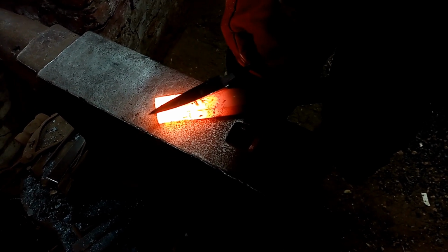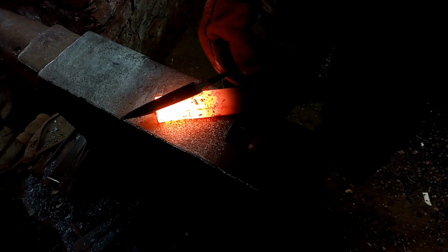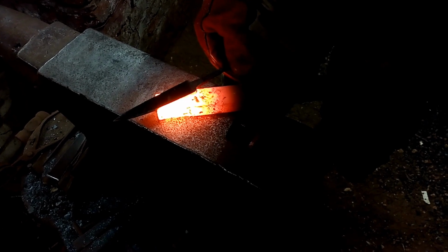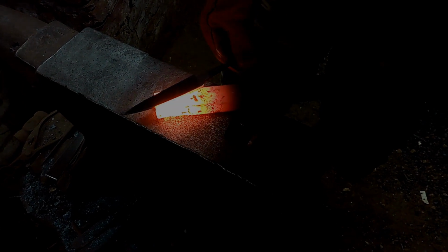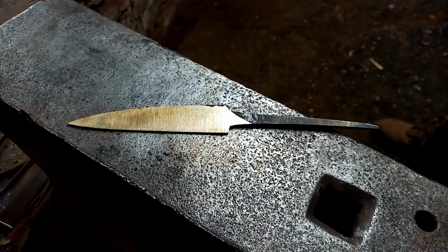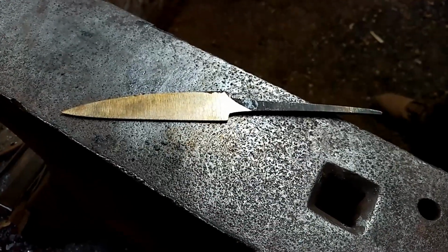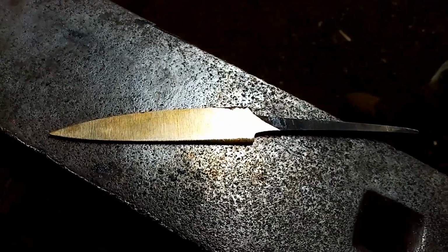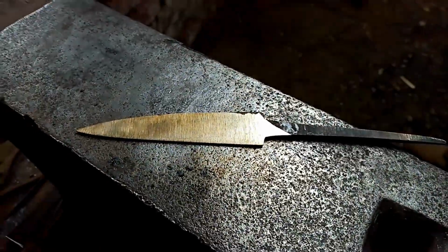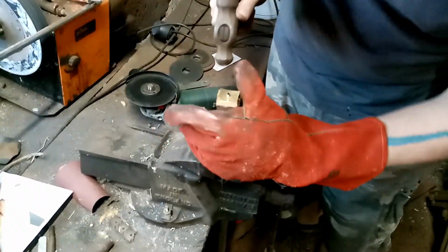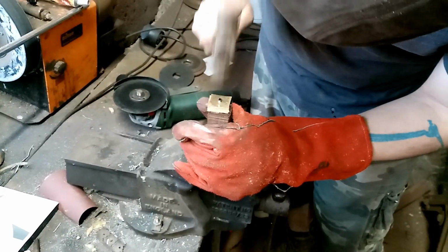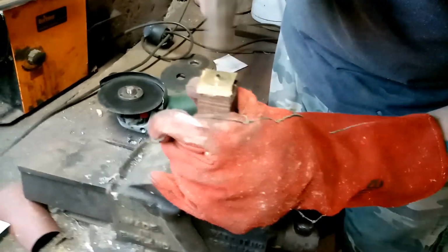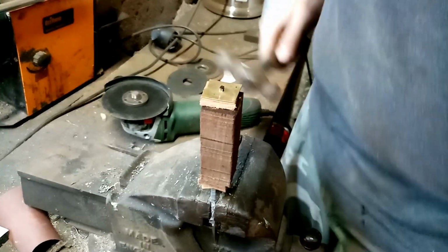Here I heat a bar up, incredibly hot, about 980 degrees, and I let the heat travel through. And what we're looking for is to make a straw colour permeate the blade. You can repeat that process several times. Usually people do it 3 times to make sure that temper has evenly passed through the blade. Again, as I said, you're aiming for straw.